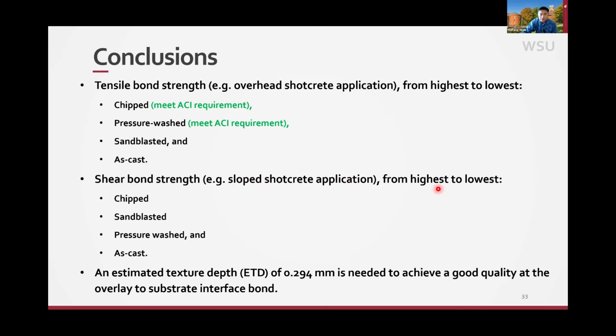on the slope method to stabilize the slope, for example, or the landslide, we see the chipped method give you the highest bond, followed by the sandblasting and pressure washing and as-cast. So apparently the surface roughness of the concrete will be critical for the shear bond. From the laser scanning method that we looked at, we need to achieve this texture depth before you apply concrete, so you can have a good bond, especially for the shear. So that's the one we recommend for the construction of the shotcrete.